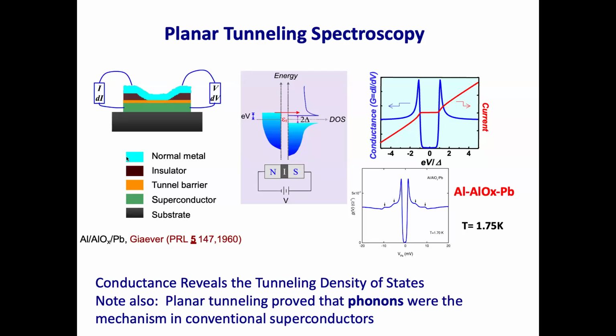And this was very nice because it's 1.7 degrees. And what we have here is lead tunneling. At this temperature, the aluminum isn't superconducting, the lead is. If you're at a lower temperature, things are a little sharper. This isn't SIS, this is NIS tunneling. Aluminum's normal. And we've seen nice sharp density of states peaks. It's not a perfect flat bottom. We kind of understand why, but what's important are those little arrows there that show those bumps.